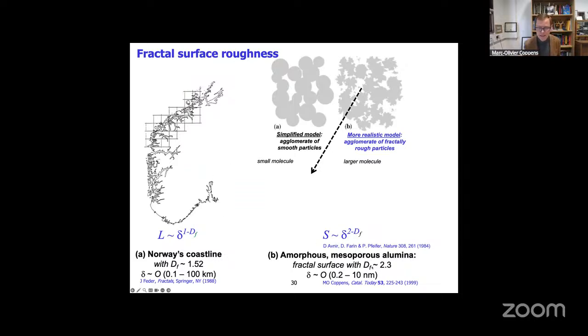It was shown already in the 1980s by David Avnir, Farin, and Peter Pfeifer that many porous materials are a bit like the coast of Norway, right? I mean, to paraphrase Jens Feder, they have this fractal surface roughness. So this is at a macro scale, the whole coast of Norway or Britain, where you have fjords upon fjords upon fjords. And so the length of the coastline depends on the resolution at which you're looking. The same thing happens even for porous materials. You zoom in on the porous material of an alumina particle, and it becomes rougher and rougher. The surface area depends on the size of the molecular probe,